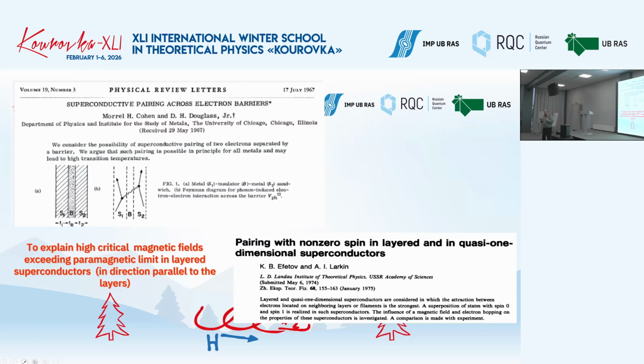And these critical magnetic fields exceeded the so-called paramagnetic limit. The paramagnetic limit means that you apply a magnetic field, which tries to orient the spins in one direction. The critical field, which is responsible for the destruction of the Cooper pairs due to the rotation of spins in the same direction, is in fact the field of the paramagnetic limit. And if it is much larger, this is bad because it looks strange if we start from the picture of singlet pairing.